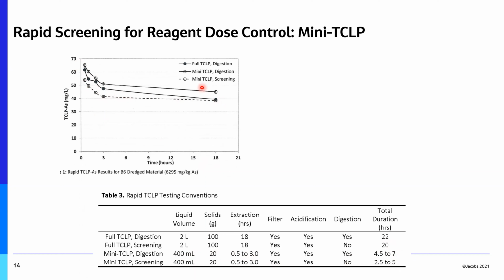The dashed line is our Mini-TCLP in a screening mode without the heating at the end for the digestion. The open circles is with the digestion. And what we find here is that for the highly impacted systems, our 3-hour Mini-TCLP basically matched our 18-hour full TCLP by the book, which was what was going to be tested on our samples in the bin. So this looked like a path forward on that.